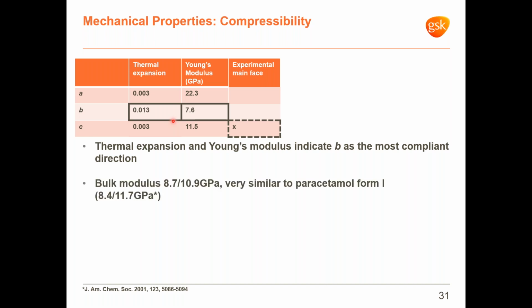Bulk average parameters provide a simple way of ranking drug substances in terms of expected compressibility behavior, though they may not be applicable in the case of extremely anisotropic morphologies. In the case of our API, the bulk modulus is 8.7, 10.9 gigapascal, reporting either the Reuss or Voigt averaged value, which suggests a similar behavior to paracetamol form 1, for which very similar experimental values are reported in the literature.